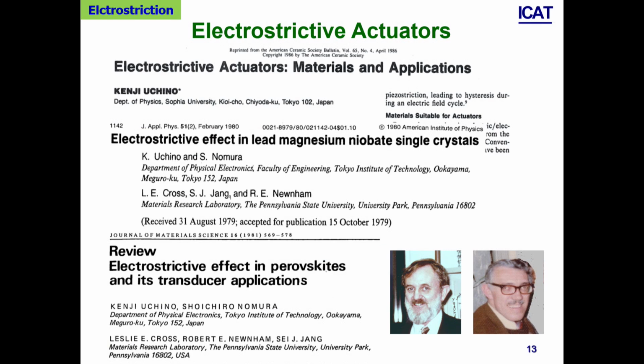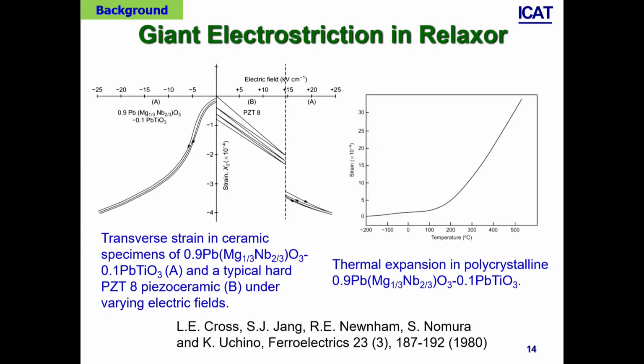So electrostrictive actuators, these are my former bosses, Cross and Newnham. So actually we discovered the electrostrictive materials, which show a large displacement. So triggering paper for the piezoelectric actuator fever. This is the end of the 70s. And the PMN-PT creates a large displacement under the electric field, sometimes higher than the PZT. So a large electric field induced strain and the small thermal expansion may be originated from micro domains. And this was suggested in the early 80s.